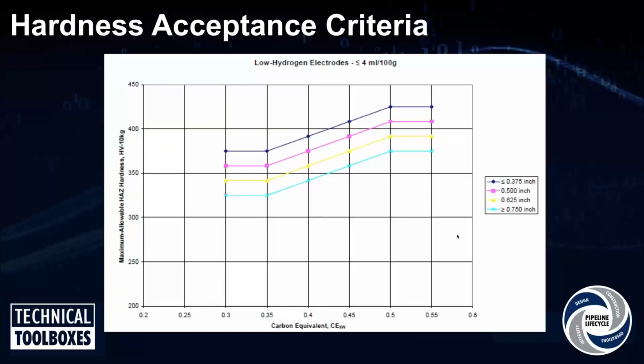This next slide shows some of this previous work in the last 10, 15 years that has looked at evaluating what would be considered an acceptable hardness. Now, as you can see from this graph, this is just one graph of the low hydrogen electrodes. And these curves are based on the acceptable hardness limit and the carbon equivalent of the material. So as the carbon equivalent goes across on the horizontal axis, you can see the acceptable hardness limit actually increases.